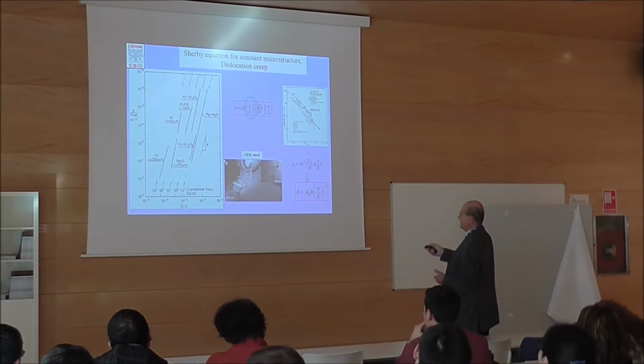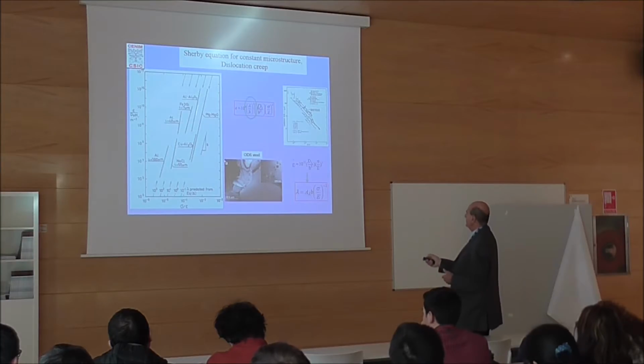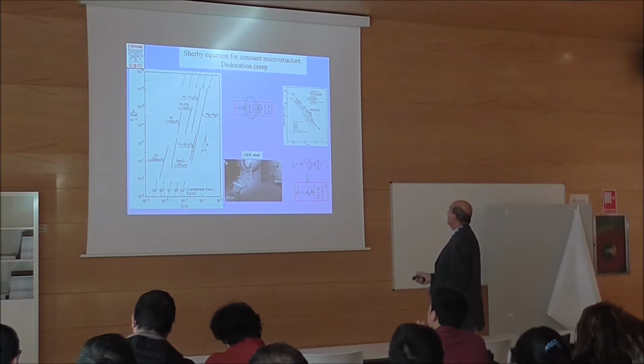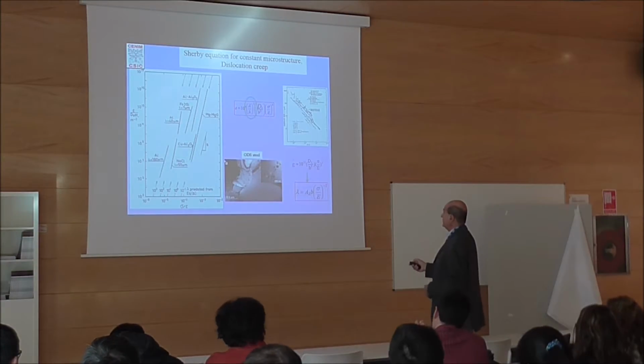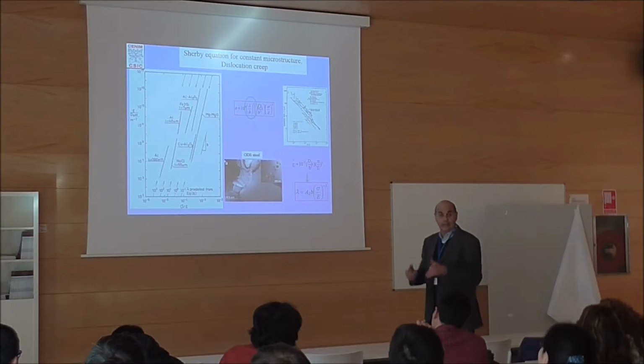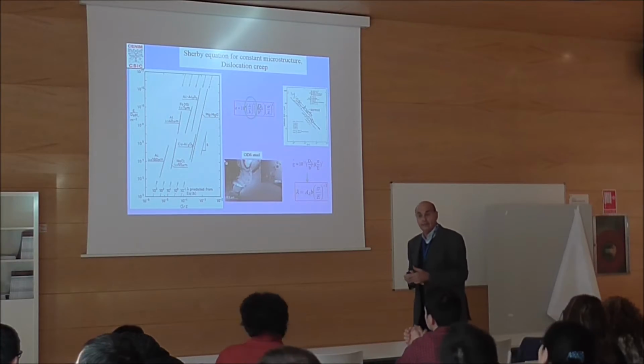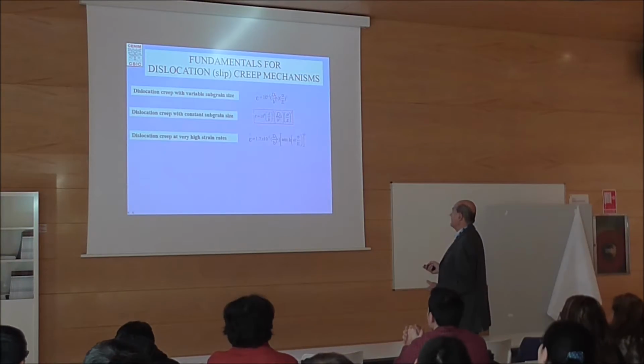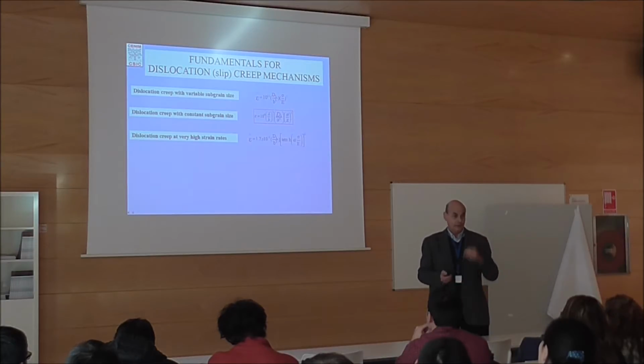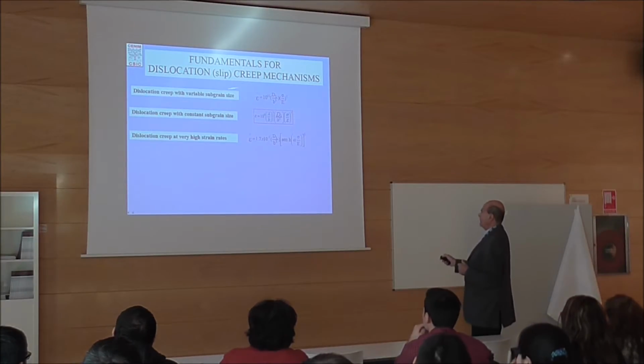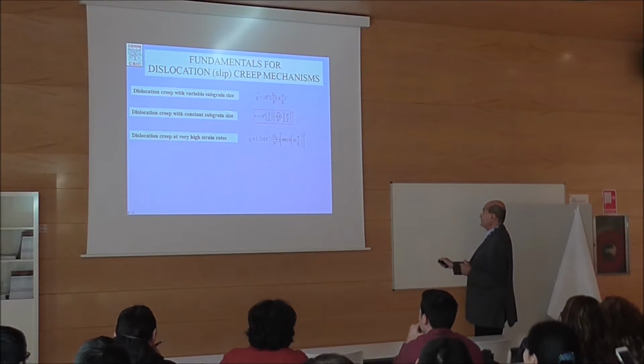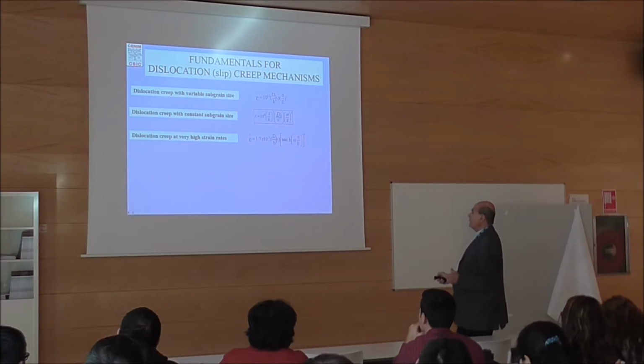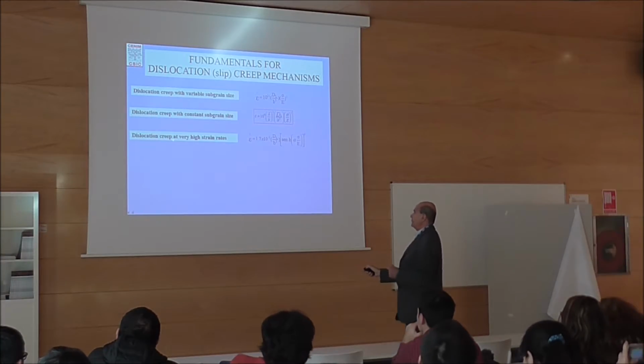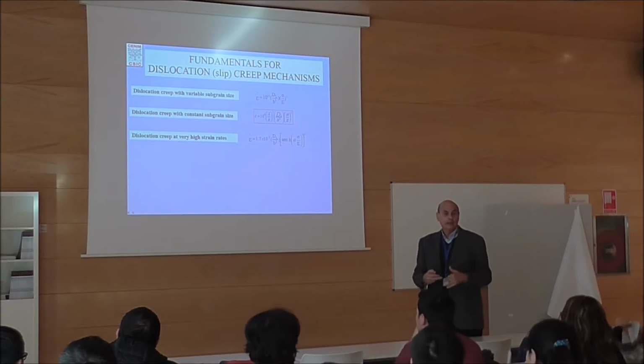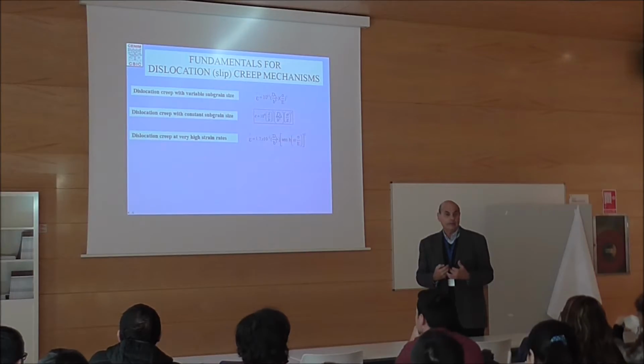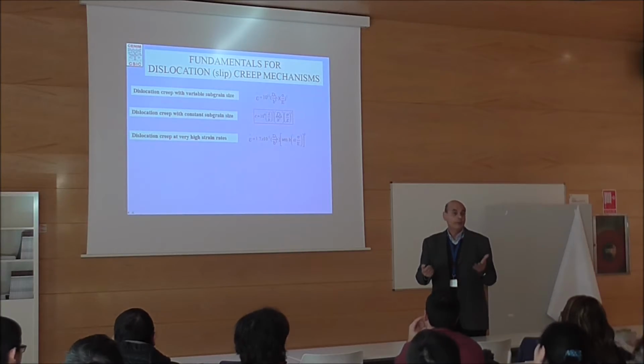So at the end, okay, there are a lot of examples. Sherby developed that in the 80s, at the end of the 70s, and there are a lot of materials. Look at this, it's mostly with oxide particles to pin the subgrain structure. So at the end we have 3 types of slip creep equations. This is the conventional one with variable subgrain size. This is what I'm just talking about here, with constant subgrain size with n equals 8. And then we have one that refers to deformation at very high strain rates, and we are talking about high strain rates above 10 to the -2 seconds to the -1.